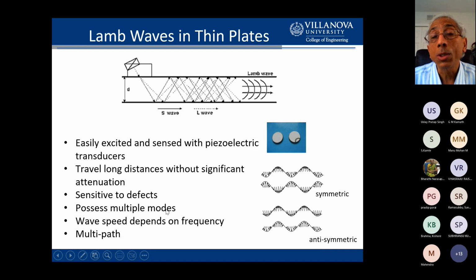And so that means you have a profusion of waves coming out and hitting your defect, if there's a defect there, and then which then gets picked up by sensing transducers. And so there's a lot of information coming at you, and sometimes it's all muddled together. And so it makes the task of trying to figure out what's happening that much harder. So that's a drawback. But as I'll show in a little while, we can actually exploit the presence of multiple modes and gather enough information that allows you to locate these defects.